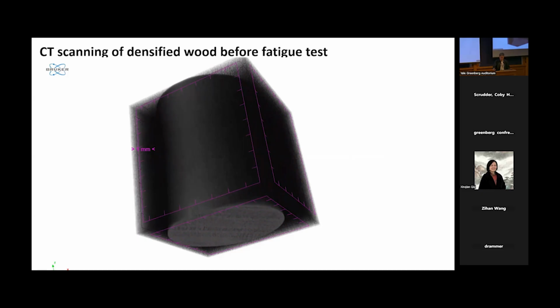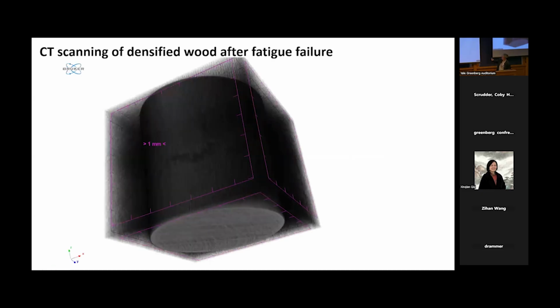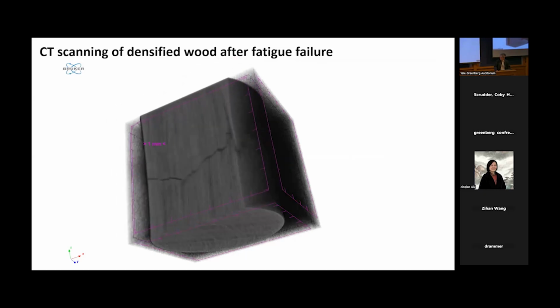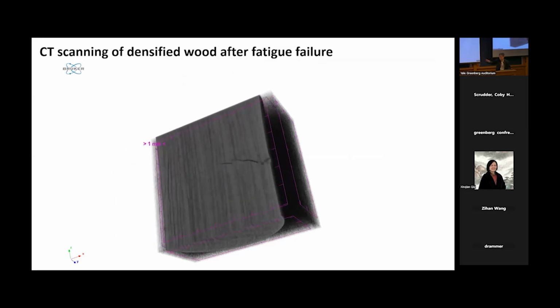Okay. So this is after the fatigue failure. Remember, it remained as one piece. We put it into the CT scanner. Now, you roughly start to see the surface crack as a shade over there. When we run through the scanning, you will see the differences here. That's a surface crack. Actually, it got into the cross section.